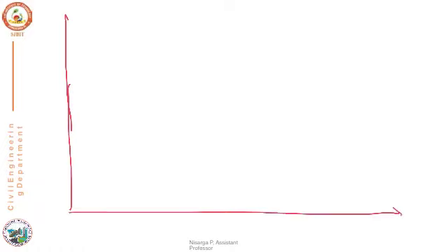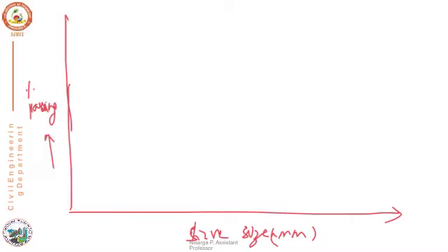Now I'll explain the step-by-step procedure of how aggregate blending will be done using the Rothfuchs method. For the method, first we have to take a graph in which the x-axis represents the sieve size. This is similar to how we do the sieve analysis graph. Take sieve size in mm on the x-axis, and the y-axis represents the percentage passing of material through the various sieve sizes.